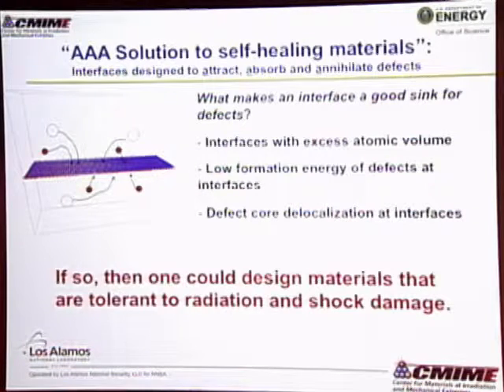So we've got what we call the AAA solution to self-healing materials. So interfaces that are designed to attract, absorb, and annihilate the defects that we put into the material as a function of irradiation. So what makes an interface a good sink? Well, if you have an interface that's got some extra room at it, that helps. If you've got a low formation energy of defects at interfaces, what that means is that energetically, defects want to move to the interface. And once they're there, if their core or their size is delocalized, which means they get a little bit bigger, it's easier to take a bigger defect next to its opposite type of defect and put them together and have them annihilate because they don't have to move quite as far. So these are the types of things that you want.